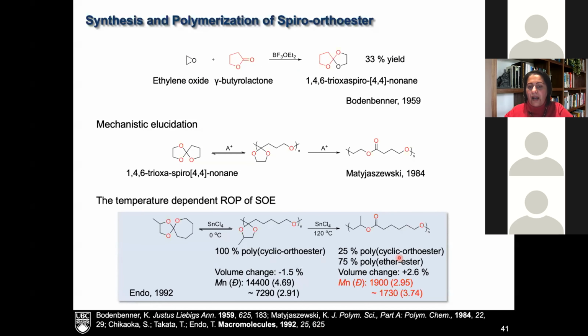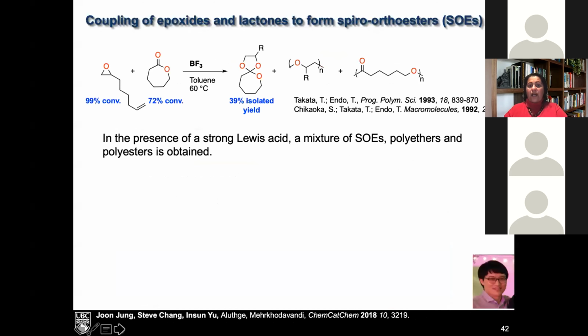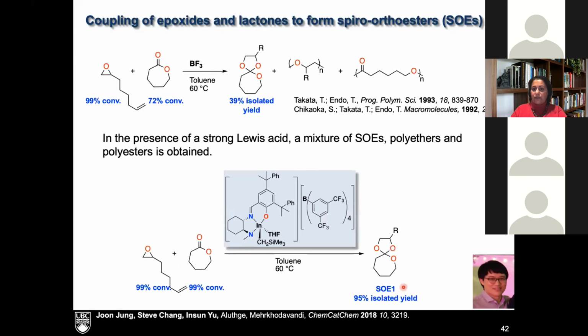But if you look at the kinds of polymers they were able to obtain, these polymers had very, very low molecular weight, really high dispersities, and it was not a very controlled reaction. So what June was able to do was, instead of doing this reaction with BF3, what happens is it's such a good Lewis acid that it forms the spiro orthoester, but it also polymerizes the epoxide and polymerizes the caprolactone. So one gets a mixture of compounds. What June did was, using his catalyst system, he was able to get 100% conversion, 95% isolated yield of this spiro orthoester. No polymerization of epoxide, no polymerization of caprolactone under these reaction conditions, which is really unheard of.